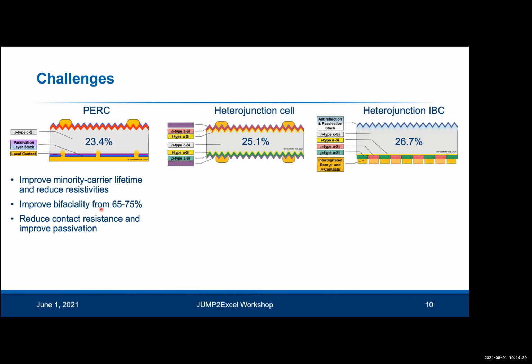There's another important factor called bifaciality, because if you think about a solar cell in a solar farm, for example, the solar cell is tilted. So you normally absorb light from the front surface, but you also get light reflected from the ground. And also at different times of the day, the sun could be on the horizon, and you could be getting light primarily coming from the back surface rather than the front surface. So bifacial devices are able to absorb and harvest light from both front and back surfaces. Because of the way the PERC cell is made right now, the bifaciality is relatively low, only 65 to 75%. So modifying this device structure to improve the ability to absorb light from the back surface as well will boost the efficiencies further.